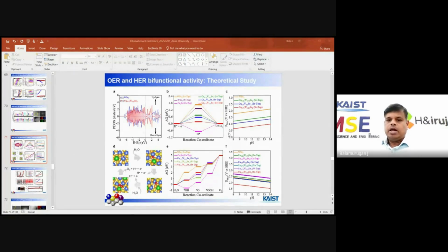When increasing the pH, the activity may be reduced, but lowering the pH gives better activity, around pH 8. In the case of OER, there are different types of mechanism, maybe the OOH mechanism. Maybe these are the rate-determining steps. Compared to the other active sites, selenium is close to zero Fermi level and a lower value. Therefore, we claim that the selenium active sites, the optimal catalyst of 0.75, 0.25 selenide, is the better catalyst.